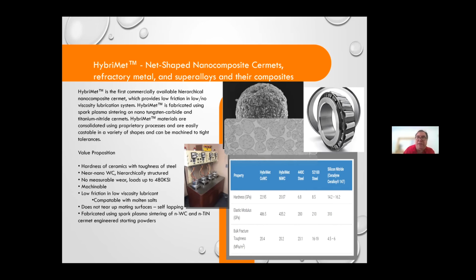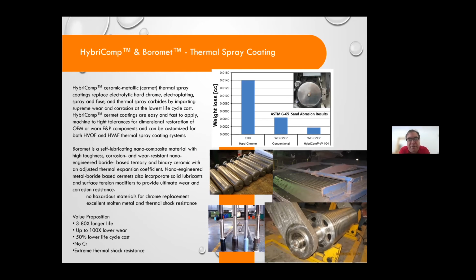We do offer these in both a spark plasma sintered version, up to 8-inch diameter parts, as well as in thermal spray packages. So here are some applications of the coatings. In sand wear abrasion, these are considerably better than hard chrome or conventional thermal spray materials, while they can take extreme stress. In the upper right, one application is in roller crushers used for sizing iron ore. These replaced a stellite weld overlay and increased the life from 2 to 3 weeks up to 6 months with just a coating. On the left, another application is plungers used in fracking pumps that are pumping sand at very high velocity and high pressures, as well as progressive cavity pumps used in steerable oil drills and downhole tools.